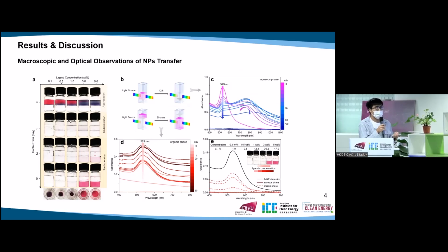And we also measured the spectrum of the aqueous phase and organic phases. As expected, there are no signals observed in the aqueous samples. However, a characteristic peak could be seen in the organic phases with higher ligand concentrations.